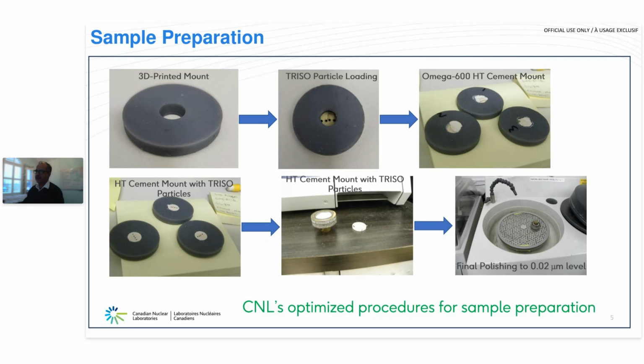And then in the second image on the top, you see basically we have these tiny TRISO particles sitting on a double-sided tape with this 3D printed mount on top of it. In the third image on the top, you see we pour a high temperature cement, Omega 600, and let it cure over 24 hours or slightly longer. And then at the bottom left, what you see is basically these TRISO particles embedded in the high temperature cement mount within this 3D printed puck that we have.